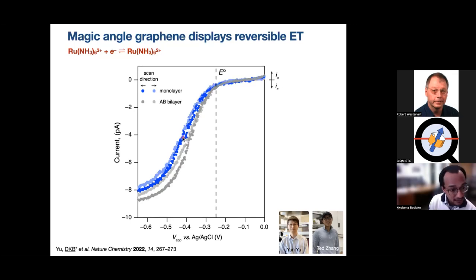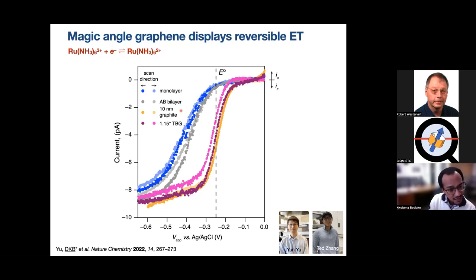So you need to put in extra potential to make the reaction take place at an appreciable rate. If you go to a bilayer of graphene, you see that curve shifts a little bit more to the right. It gets a little bit easier, or kinetically more facile. And this is simply because you have more densities of states for bilayer graphene than monolayer graphene. If you go to bulk graphite, sure enough, you see that this S-shaped curve is centered at that thermodynamic potential, telling you that you're at the reversible limit. There's a minimal activation energy barrier for you to overcome to do this chemistry. So what happens then if we take two layers of graphene, just like the gray, but instead they are twisted to about 1.1 degrees? Now we see that actually the kinetics behave the way bulk graphite does for all intents and purposes. We have effectively reversible kinetics at this surface.